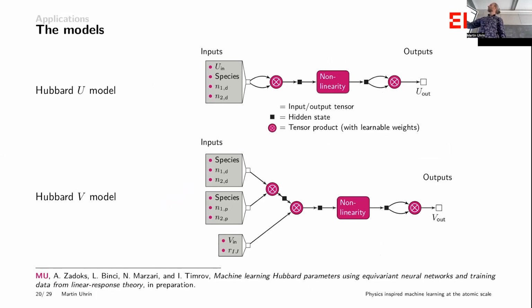So yes, your guess for the U that you started with, which can be just 0 if you just don't know. You just say, okay, it's 0, I don't care. The species that you're looking at, so whether it's nickel or iron or manganese, whatever it is. And then the 2 occupation matrices, these calculations have spin polarization, so there's spin up, spin down. And then we pass through these non-linear neural network parts. So this is very much the same as you see these diagrams like I've shown, where you have your neurons arranged in layers. That's what's going on here. And then I get my final U value out from this.